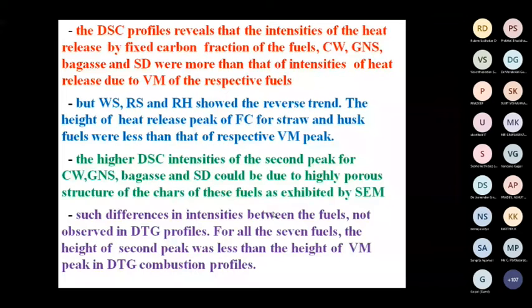The higher DSC intensity for the second peak for coir waste, groundnut shell, bagasse and sawdust is due to the highly porous structure of the chars of these fuels, as exhibited by SEM. We will see the SEM picture. Once volatile matter is released, we call it a char. The chars of coir waste, groundnut shell, bagasse and sawdust are highly porous.